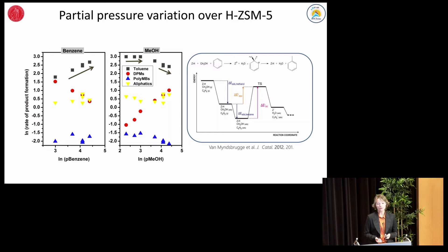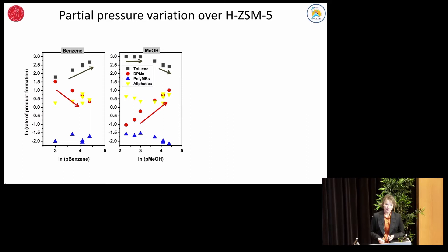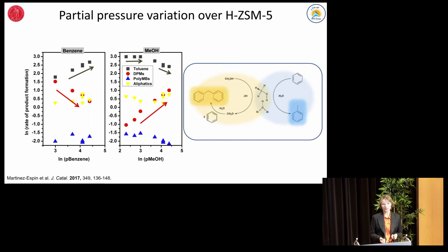However, upon further increase in methanol pressure, a negative influence on toluene formation rate was observed. Considering the formation rate of diphenylmethane, its formation rate is negatively correlated with benzene pressure and positively correlated with methanol pressure. Overall, the partial pressure variation experiments show that the two reactions proceed on the same active site. Indeed, a methoxy group or methanol sorbed on the Brønsted acid site may react either with benzene to form toluene, or with methanol to form formaldehyde and subsequently diphenylmethane. Such dehydrogenation reactions constitute a first step in the conversion of monoaromatic molecules towards coke.